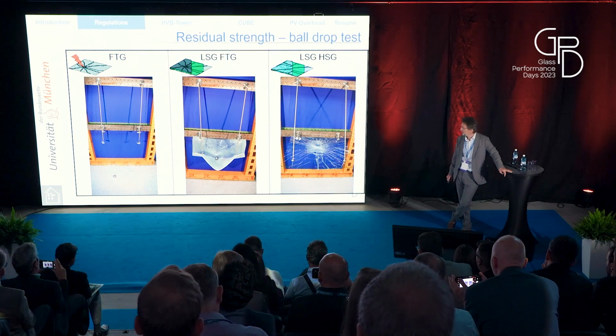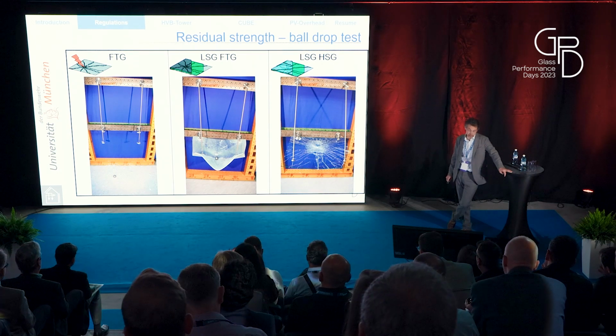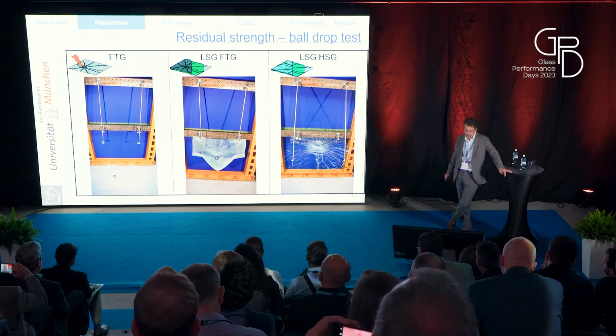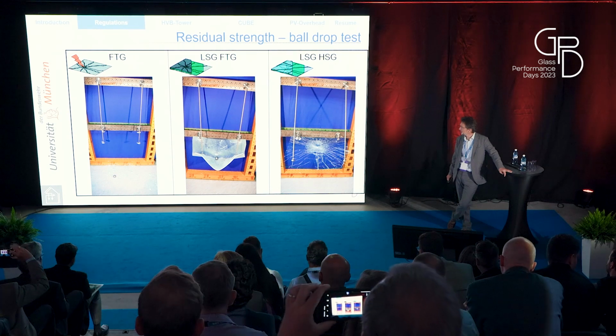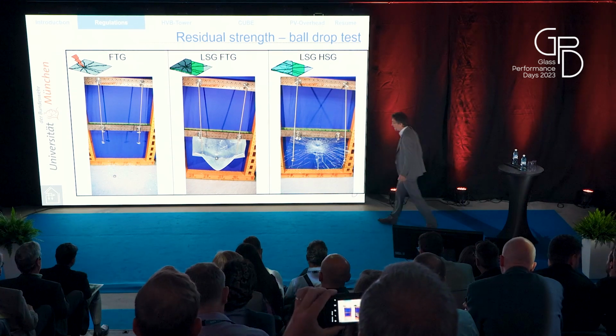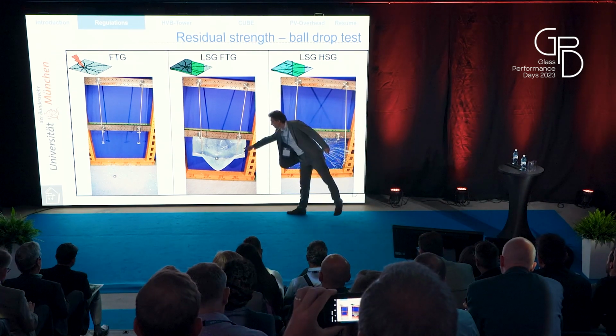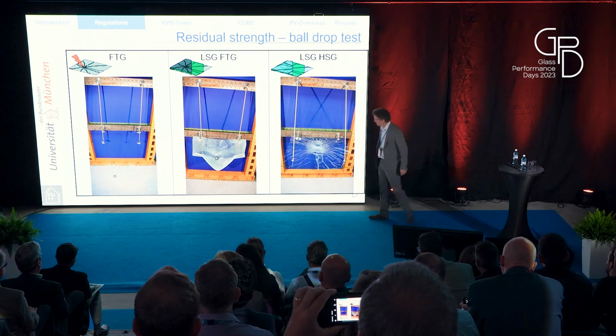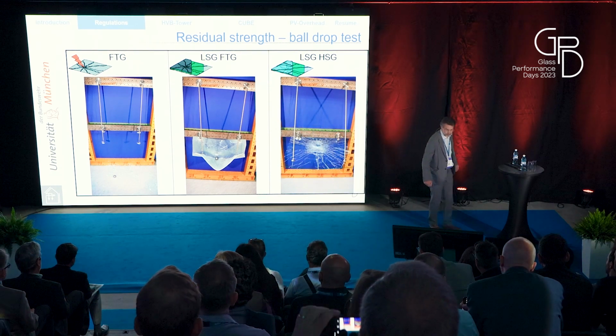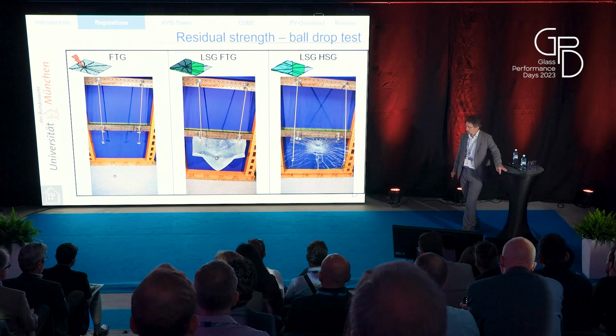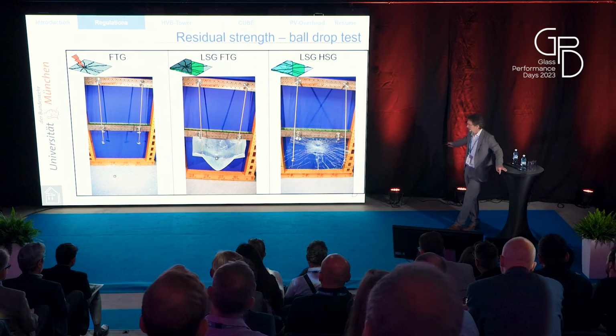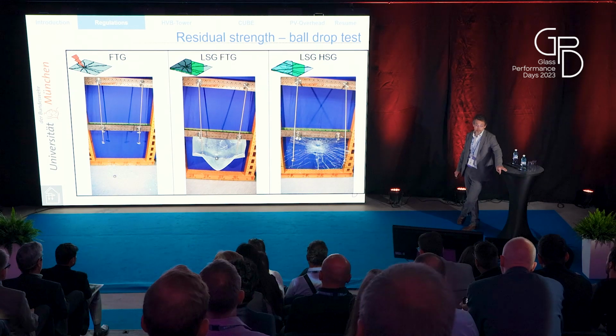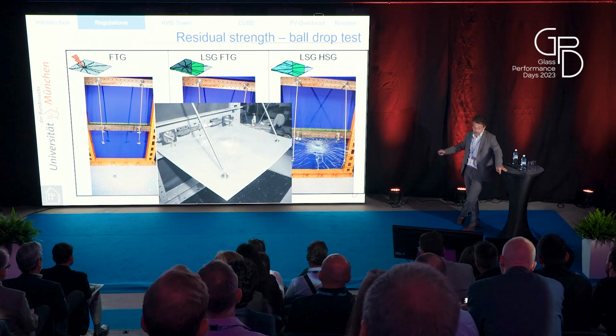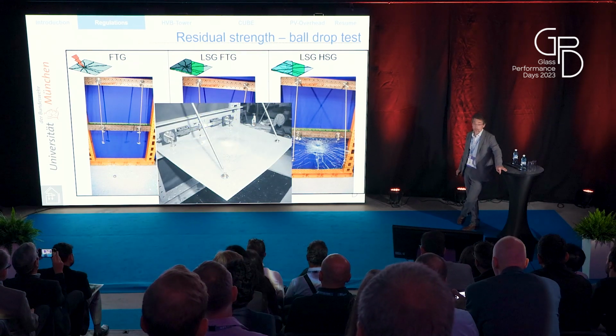This is well known. If you have fully tempered glass, there is no residual strength. If you have fully tempered with softer laminate, you have big deflections. If you have heat-strengthened glass with PVB, for example, you have a good behavior after breakage, so you can still open the door beneath this canopy and leave the building. And if you change the interlayer material to a stiffer material, this also could work with fully tempered glass. So you just have to know what you're doing.